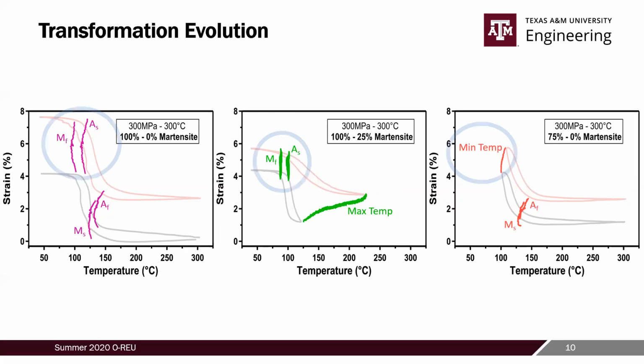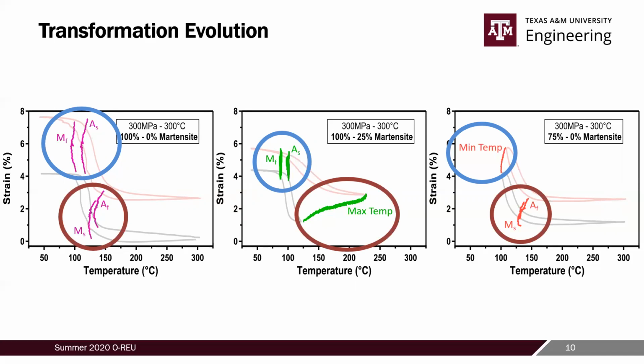So these temperatures here, circled in blue, follow similar trends, and these other temperatures here, circled in maroon, also follow similar trends, but those are slightly different than the blue trends. It kind of looks like these maroon ones change a bit more than the blue transformation temperatures. So these relationships will all be helpful in developing a theory for the micromechanical mechanisms behind partial cycling.